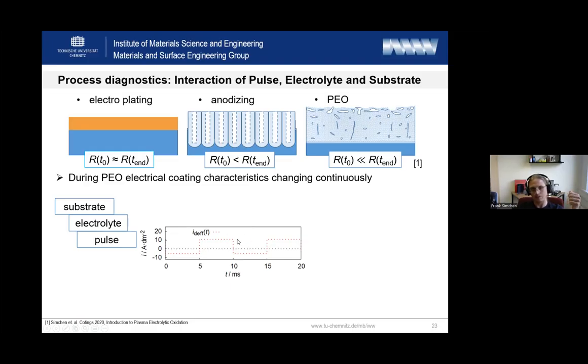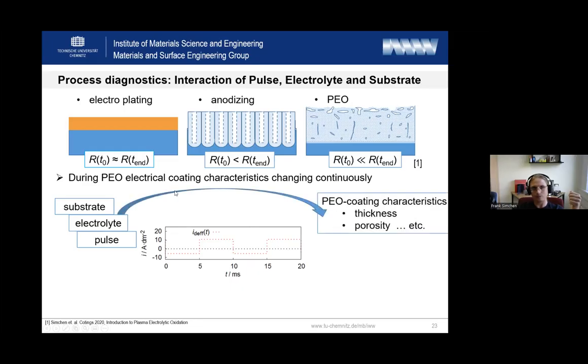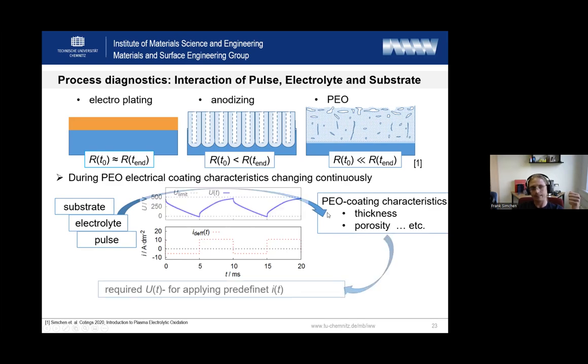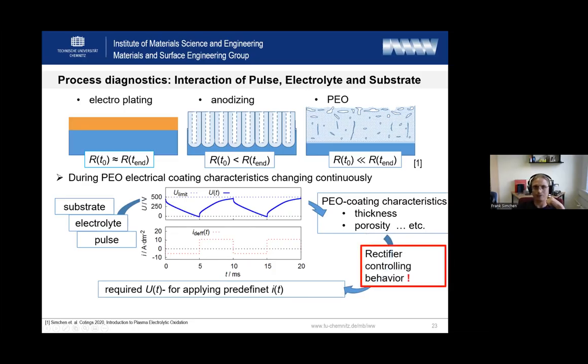And this we see when we measure our electrical parameters. So maybe we define a rectangular pulse, but this rectangular pulse leads to a PEO coating with certain characteristics, with a certain thickness and porosity. And they, again, interact with the rectifier controlling behavior, which is the most undervalued input parameter of your system, because usually you don't know by yourself how the rectifier controlling behavior is. The company who built this rectifier will not tell it to you.